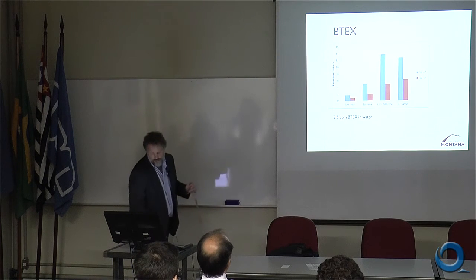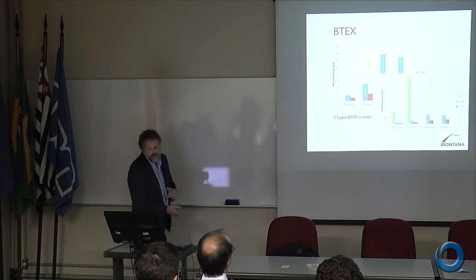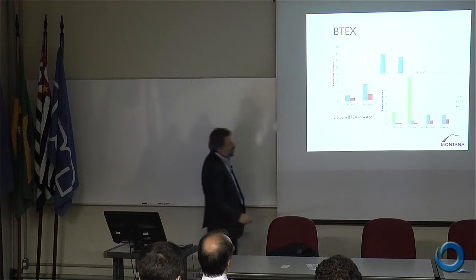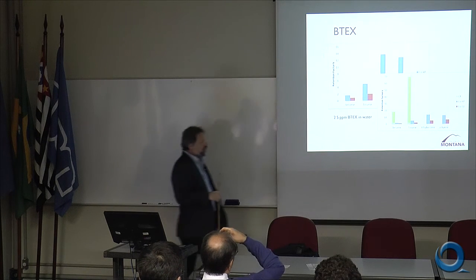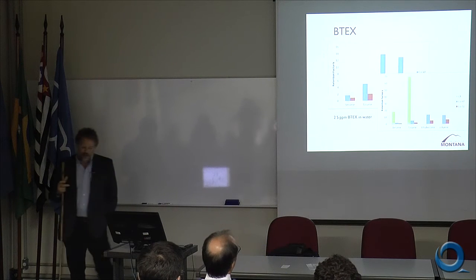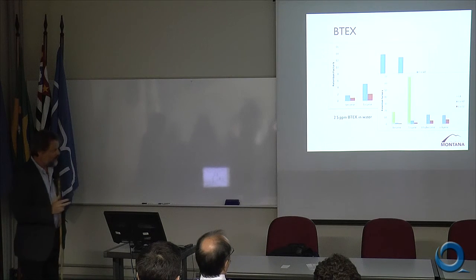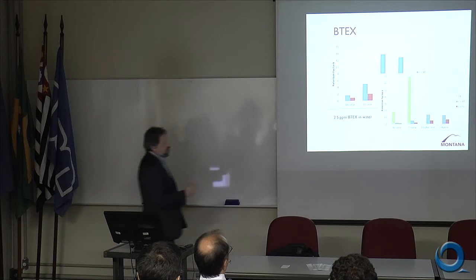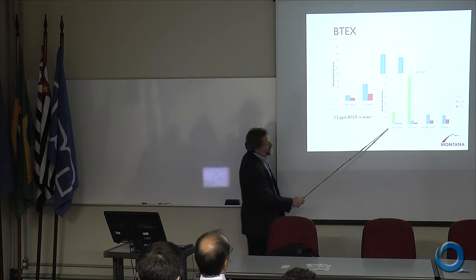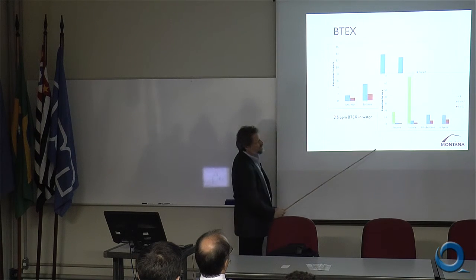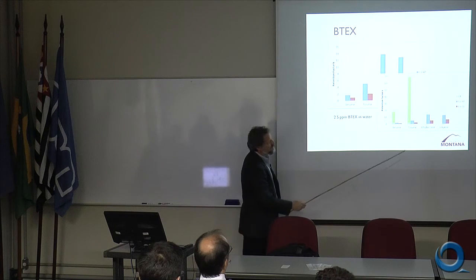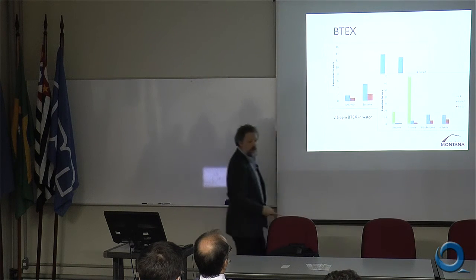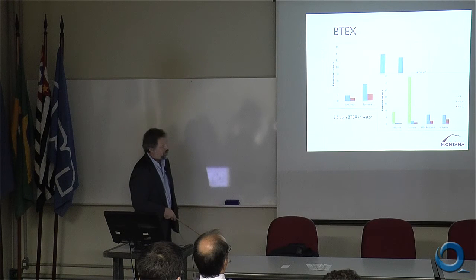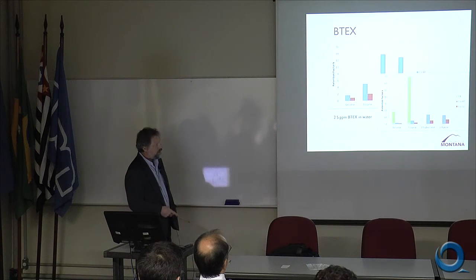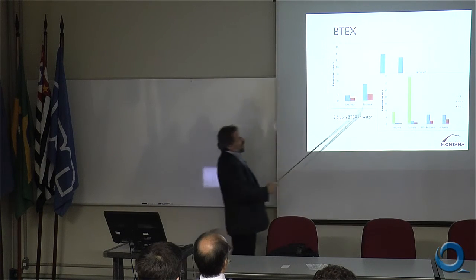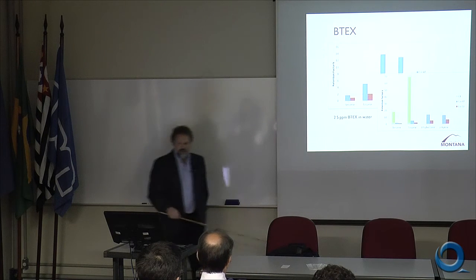47 is outperforming 32. And then if we compare that to commercially available materials, so in this case we're looking at an octyl C8 modified silica. Benzene has much higher retention on the C8, toluene much higher retention. For ethylbenzene and xylene, it was above our ability to measure it, so it was very high retention.